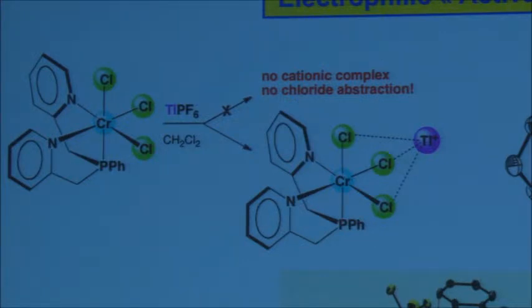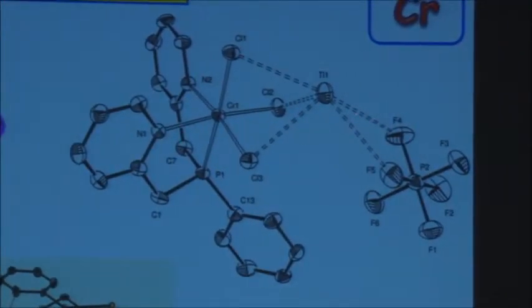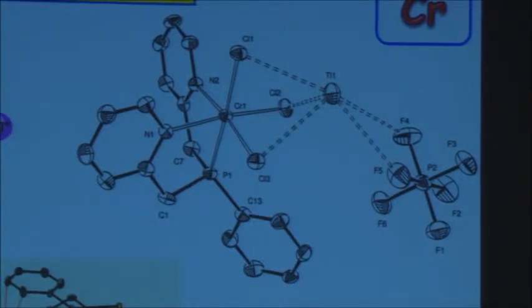Like St. Thomas. Sometimes I like to see things. Otherwise, I don't believe them. Well, indeed, there was no precipitation of thallium chloride in dichloromethane. But he was able to isolate compounds from that and single crystals. And the answer came, the thallium has not abstracted any chloride. It has coordinated to this free chloride to give this sort of product, and the structure is shown here, with the PF6 stabilizing with fluorine bonding the thallium center. It forms sort of a dimeric structure in the solid state, which is quite nice, but I don't want to go into the detail.